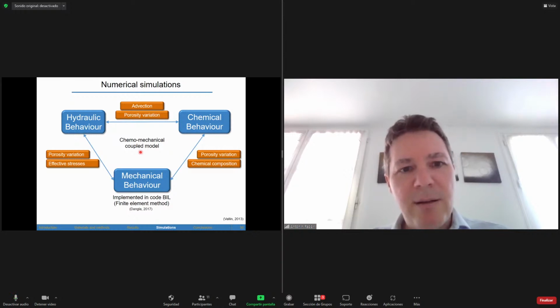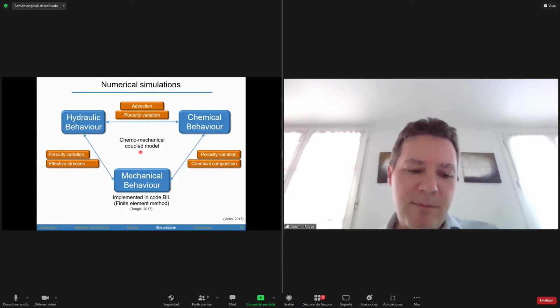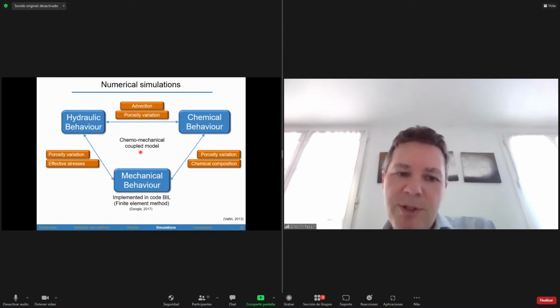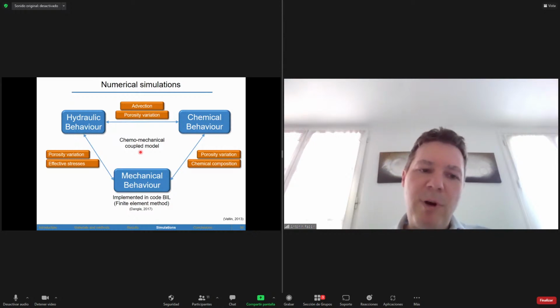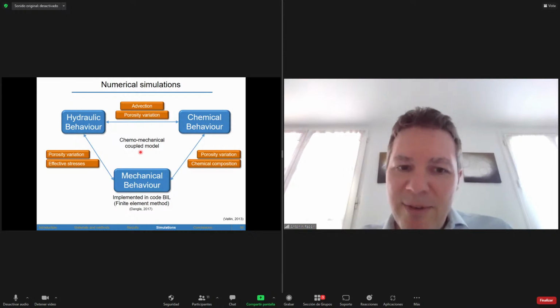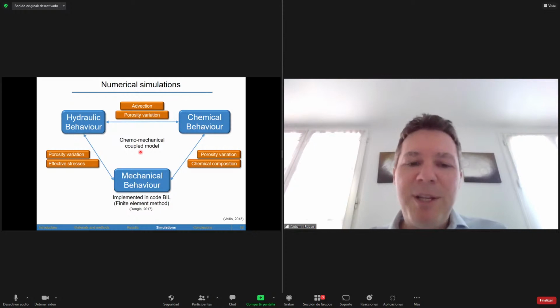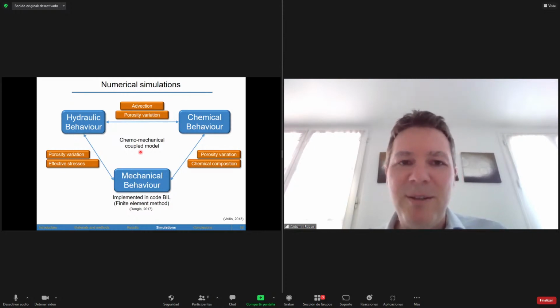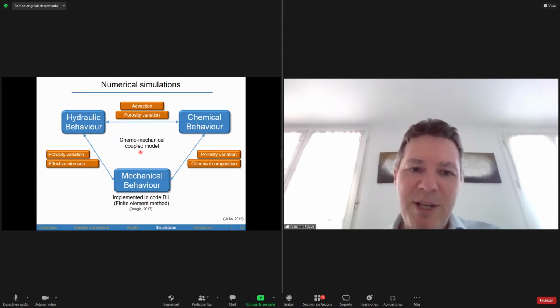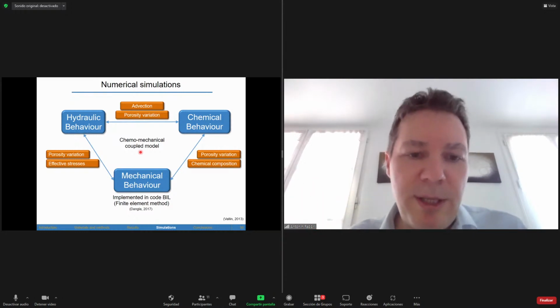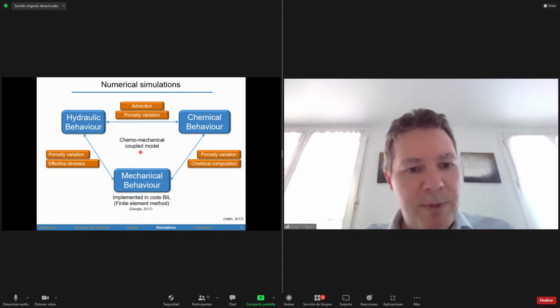Because I think that in the code you can consider some kind of reaction kinetics, and using kinetics can be interesting if you want to see the dissolution front and the carbonation front, to have a better separation between both, and maybe to capture the porosity variation in the uncarbonated zone, which is one important thing that you underlined in your experiments. If you want to model that, you need to use some kind of kinetic law, and maybe the equilibrium will not be good to see that. It's only my impression, but maybe I'm wrong.